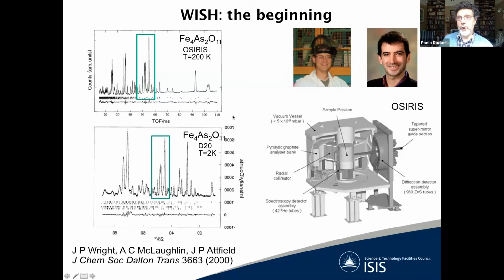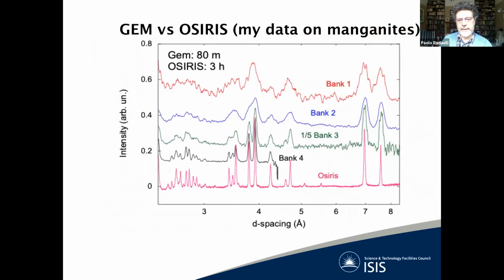And D20 was and is considered a very powerful medium resolution diffractometer. But OSIRIS, particularly at these short time of flight, but also the longer time of flight, as you can see from the box that illustrates the same magnetic peaks, has a much better resolution. And then, of course, if you go even further to the left, you see a complete resolution of the pattern, whereas on D20, it's basically just oscillations.